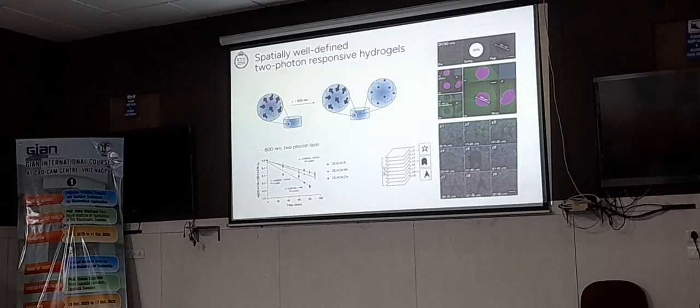And using this, when you use a confocal, you can also go into different layers in the Z direction, right? I'm sorry, I should have made these a bit larger, but I can tell you what it looks like and what I want you to see. So what we did now was that we irradiated in the Z direction. We didn't irradiate on the top, but this is a star that we irradiated between 11 and 20 micrometer down.